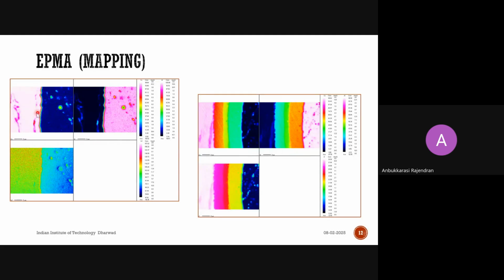Okay, so this is the same copper aluminum dissimilar joint. I plotted this mapping for the copper variation. So this is the copper side, and I could see the enrichment. This color code gives me the information that the pink color is the maximum, highly concentrated region, gradually decreasing. Then the dark color is an indication of a depleted zone. So in this particular region, the copper variation is high on this side and low here, because this is the aluminum side. So when I plot aluminum for the same selected area, aluminum is depleted here or not available, and aluminum is high in this region. Whatever intermixing happens at the interface, you can see the diffusion layer with the intermediate color, 50-50, which means some diffusion I could see at the interface.